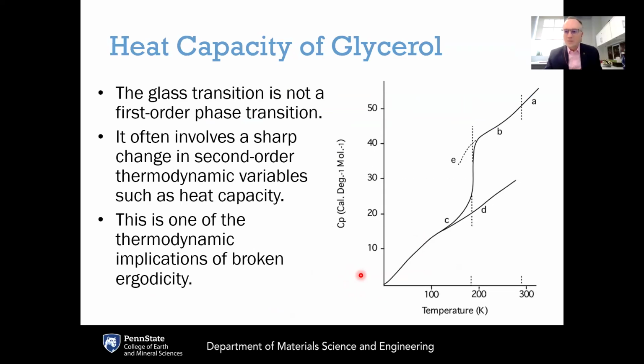This shows you an example of the thermodynamic consequences of the loss of ergodicity. This is the heat capacity curve of glycerol, which is a simple organic glass former. What you see is the heat capacity as a function of temperature. This shows the liquid at high temperatures, and then as this liquid is cooled below this temperature, which is like 180 something Kelvin, this is the glass transition range for glycerol.